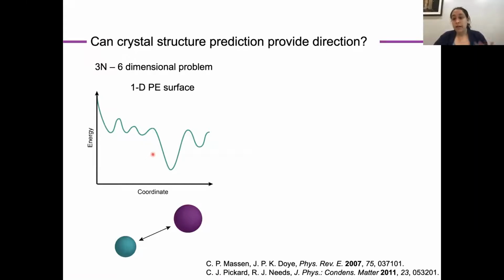For example, if there is a stable configuration to be found, it's going to be at the bottom of a potential energy well, where the deeper the well, the more stable the structure. However, there might be multiple of these wells corresponding to local minima as well. Furthermore, we know that as we move those two atoms apart and bring them back together, we wouldn't expect small changes in distance to introduce discontinuities in the energy of the system. That in turn places a limit on the curvature connecting these local minima as well as to this global minimum. And so that has a profound implication on what this phase space looks like. That means that in general, the more stable the structure, the deeper the well that it lies at the bottom of, the larger the amount of phase space that this well takes up. And so that's going to underpin our computational approach.